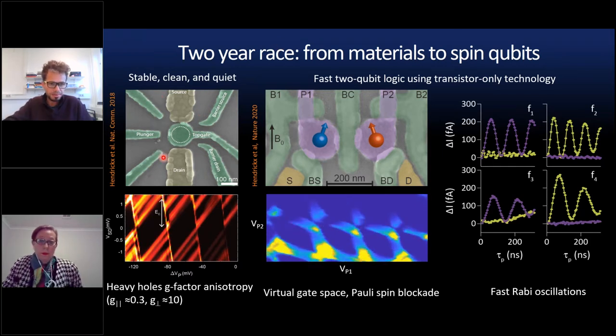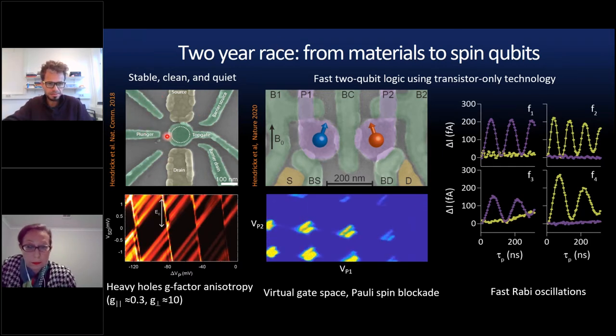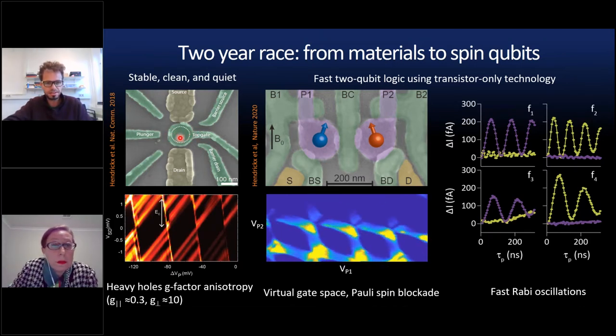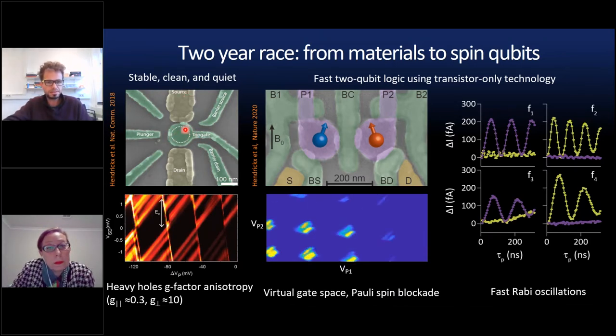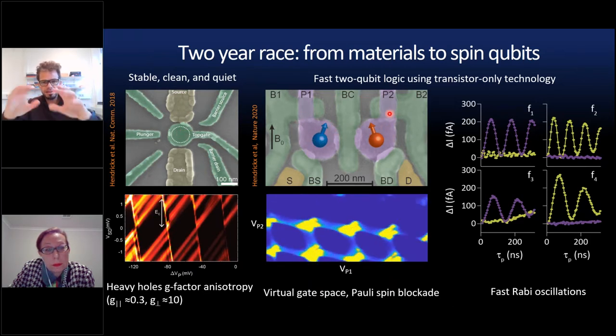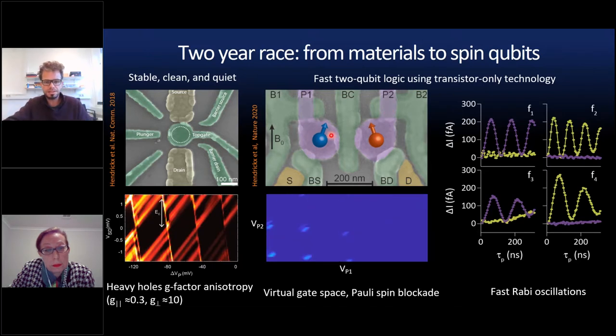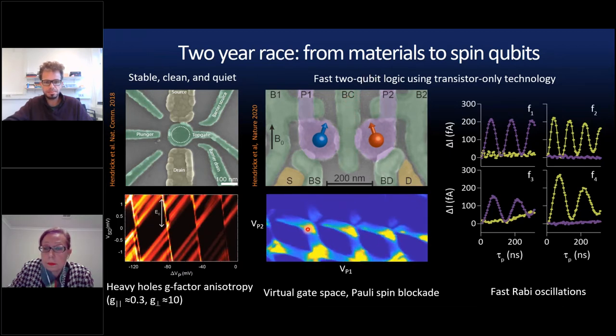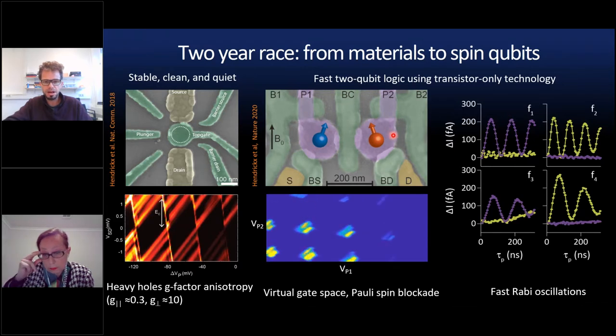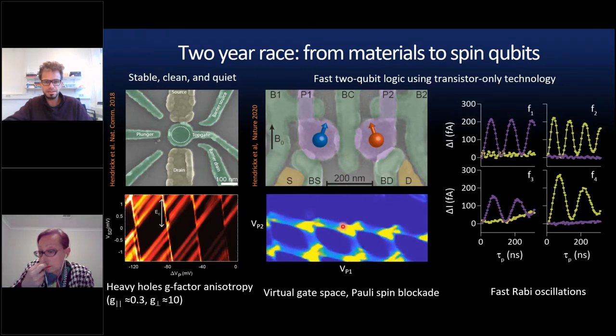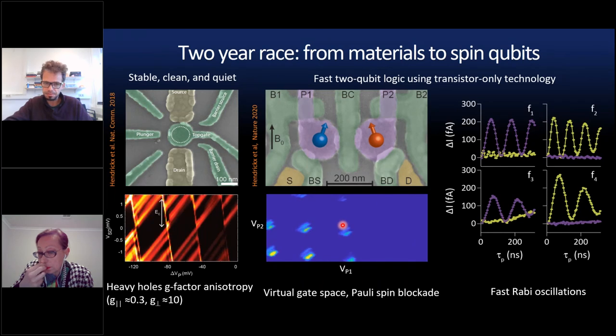Here you see a structure where with nanoscale gates from the top, you can confine charge. And it's basically like a transistor with source, drain and a gate where you can isolate these single charges. And with these other gates around, manipulate the coupling between the charge and really measure signatures of forming quantum dots, where here, upon changing this gate in between, you can tune transport from being like a single large quantum dot to being two isolated quantum dots.